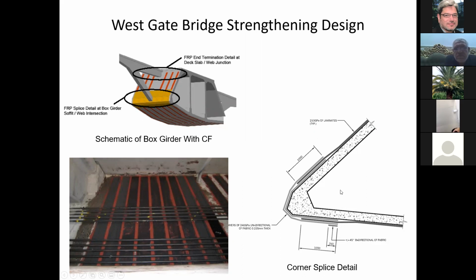And the technology that we introduced to this is what's known as bidirectional fabrics, to prevent what we call delamination, the delamination of the carbon fiber from the concrete surface. The technology that we developed was responsible for reducing the amount of FRP for this bridge by about 30%, which was quite significant, both in terms of workmen, in terms of the amount of work, time of work, as well as in terms of the cost itself.